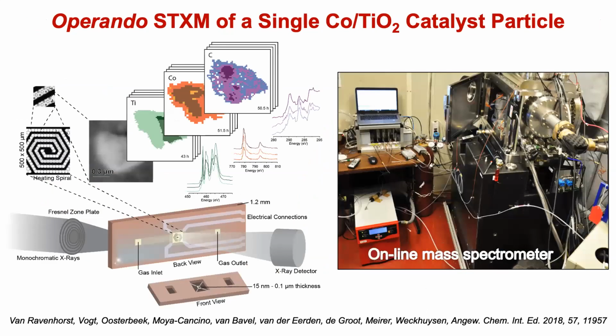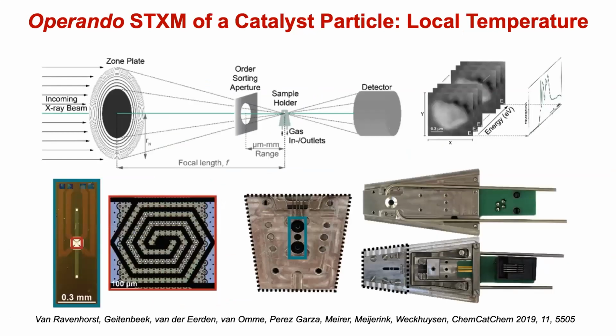If you do that, and there's a slide I showed you before in my previous talk, which I gave here at Zurich, this is the setup. You can measure titanium, cobalt, carbon, and whatever. But what you did actually not ask anything about is, yeah, but this is a spiral. And so here you see the spiral on the left bottom. You see a platinum spiral, and there in between these windows, there your catalyst particles are.